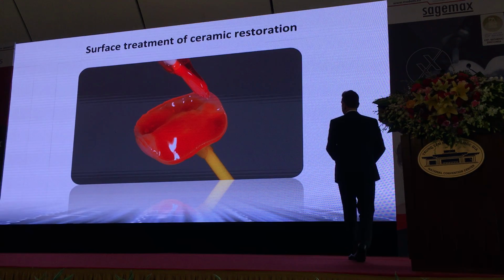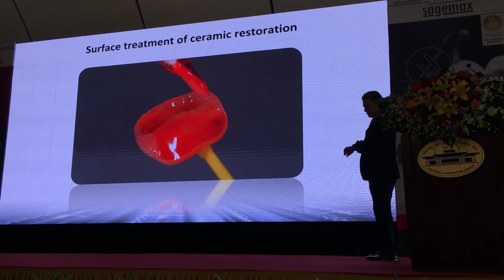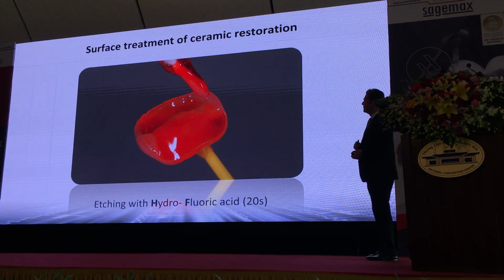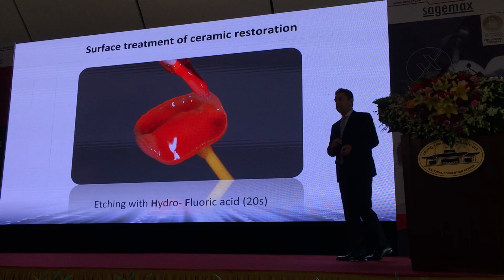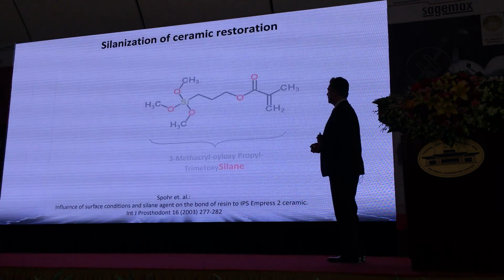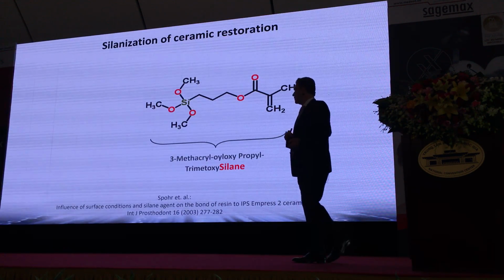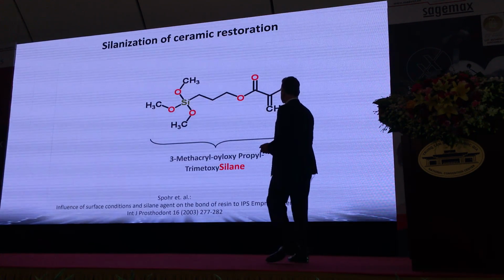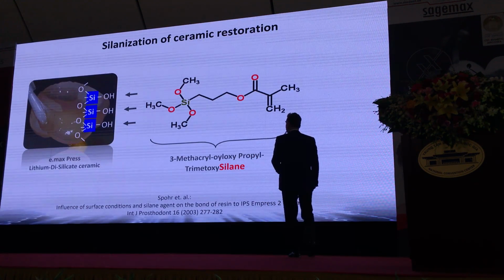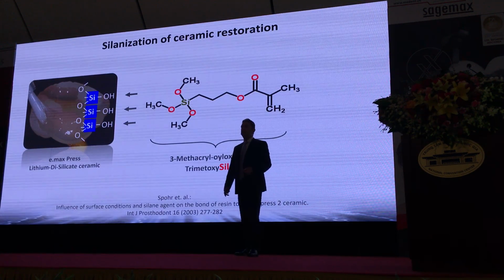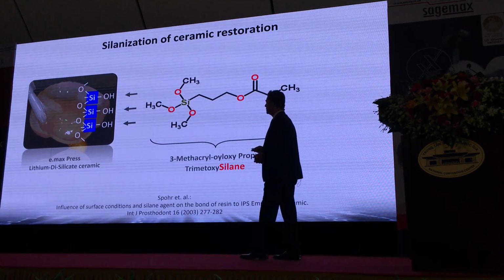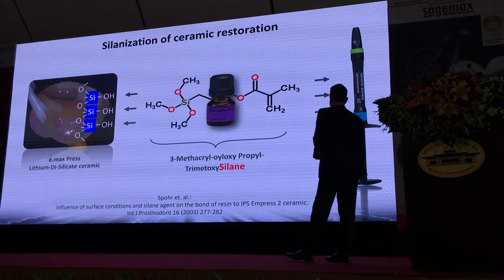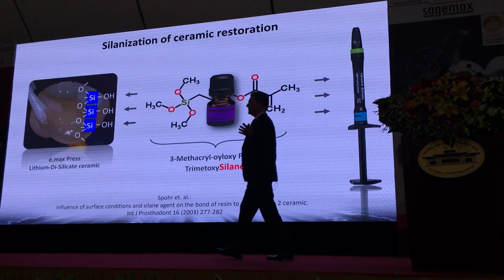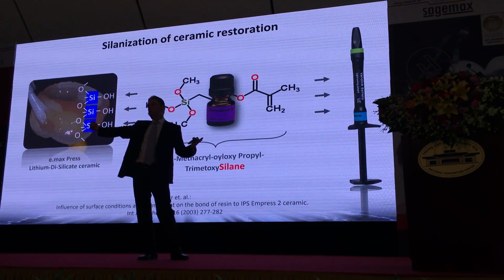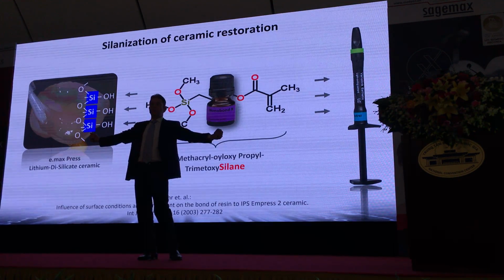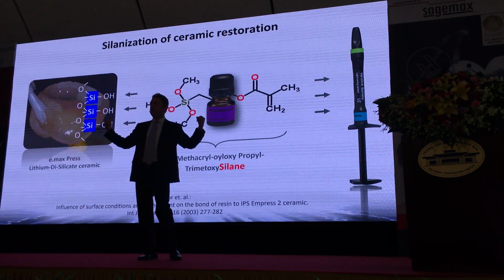Okay, so now this is the pre-treatment of the E.max restoration. We use hydrofluoric acid for 20 seconds, and we rinse that off. You can see now we need a chemical bond to the ceramic, and we use a silane. You can see this is the silane methacrylate. The silane methacrylate, for example, we have it in Monobond N, and it can connect to the ceramic, and it also can connect to the cement. So the silane has two arms. One arm to the ceramic, and one arm to the cement, and holds it together. Okay?